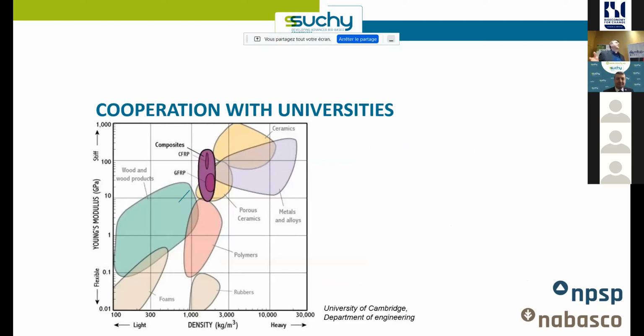And if we want to make the shift from university to our clients, we always have this discussion about material selection. For this, we use Ashby diagrams a lot. Here you see the diagram with stiffness on the vertical axis and density on the horizontal axis. For most of our products, especially moving products like scooters, we try to optimize the ratio between density and stiffness. And Nabasco you see plotted here, in between the wood and wood product materials and the composites and metals. So it's less stiff, but a lot lighter than metal, and it's a bit heavier, but also stiffer than wood. And it's a bit lighter than the glass fiber composites.